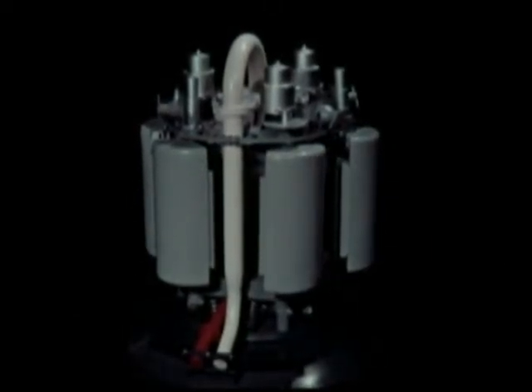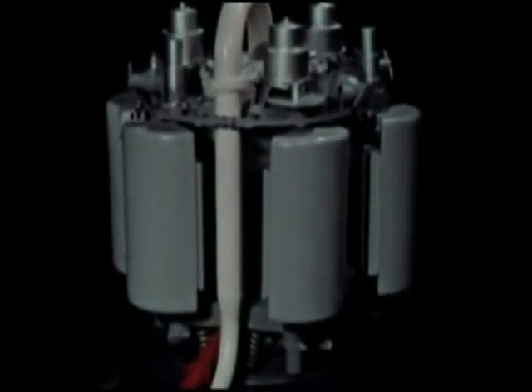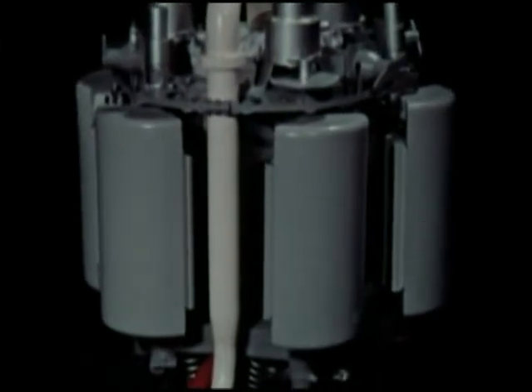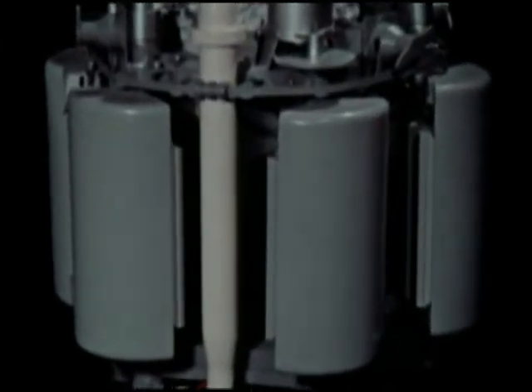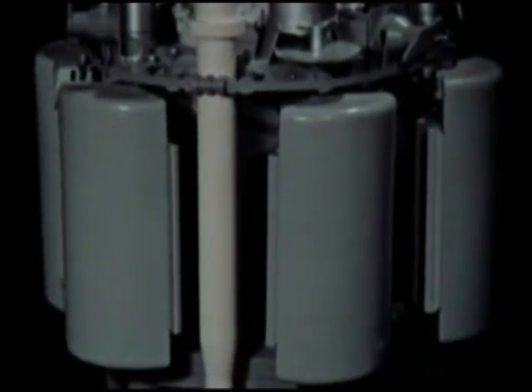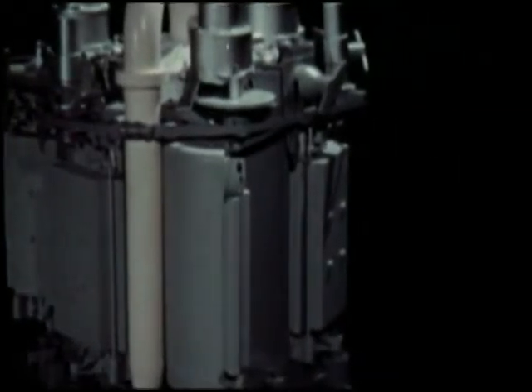The reactor is designed for a NaK coolant outlet temperature of 1300 degrees Fahrenheit with a controlled dead band of approximately plus or minus 20 degrees Fahrenheit and a coolant inlet temperature of 1100 degrees Fahrenheit. During rated power operation, the NaK coolant flow rate is approximately 13 pounds per second with a pressure drop of less than 10 psi through the nuclear system. The reactor is designed for continuous unattended operating life of 10,000 hours in the space environment.